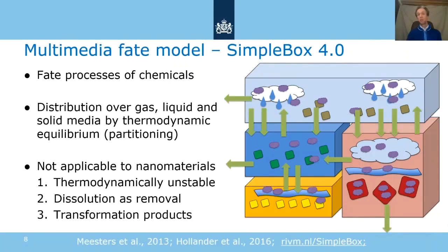Now, why would we need to make this model fit for nanomaterials? Well, the conventional SimpleBox, or SimpleBox 4, is of course fit for use with chemicals, but these are dissolved, for example, organic compounds, and they distribute themselves between the gas, liquid, and solid media. And this is described using thermodynamic equilibria with partitioning coefficients and so on. So for nanomaterials, it was found that because they are a particle, they're solid, they are thermodynamically unstable, so they will not follow partitioning coefficients known for other compounds.